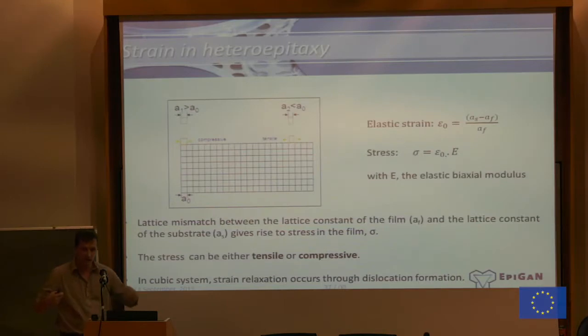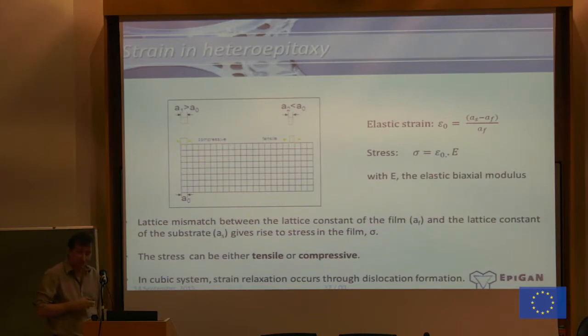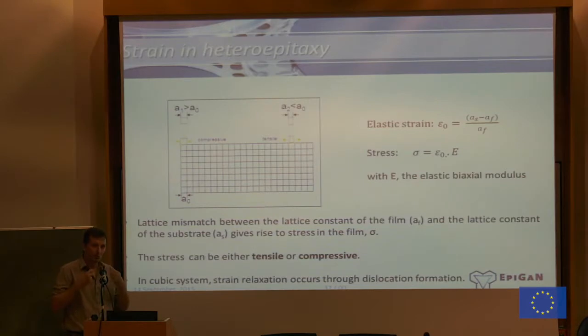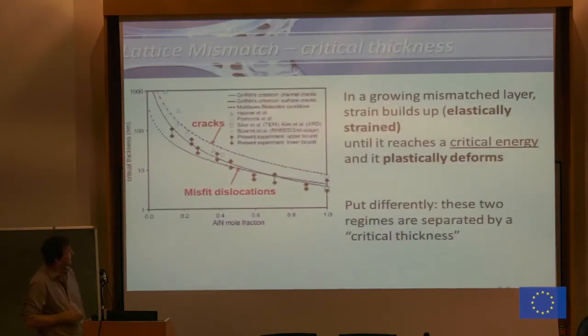So, on the one hand, it can be compressive strain, in this case here, or it is tensile strain in the other case. And the important thing is to realize that it requires energy to do so. And as you build up layers of this strained material, more and more energy will be built up into this crystal. Right? So it's really a strain energy that is inside. Now you would say, okay, that's not a problem. The crystal can handle that. Now the problem is that it is not. So if you grow these strained materials, as you keep on growing, the energy that is built up in the strain grows and grows and grows and grows.